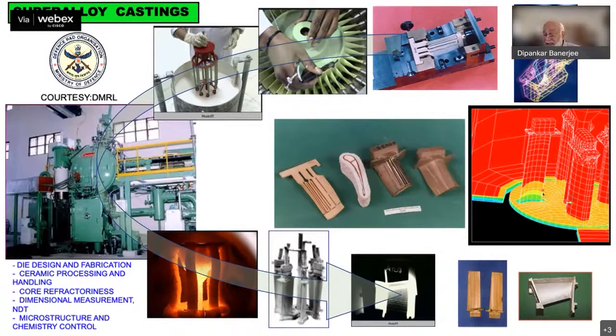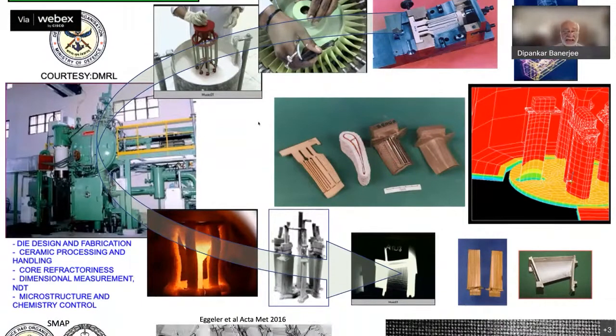And you control the thermal gradient such that the heat direction is unidirectional to provide you with the columnar grain structure or even the single crystals. Okay. And this is a truly complex technology. You think about it, you're pouring metal at about 1400 degrees centigrade into these hollows which resemble this blade shape, which are sometimes a millimeter or less at the leading edges. And you have to preserve the integrity of the ceramic mold and the core when you're pouring at 1400 degrees centigrade. And you have to accommodate anisotropic metal shrinkage, core shrinkage, mold shrinkage to achieve the final tight tolerances which the aeronautical engineer requires in his aerofoils. But we've learned to master that technology as well.